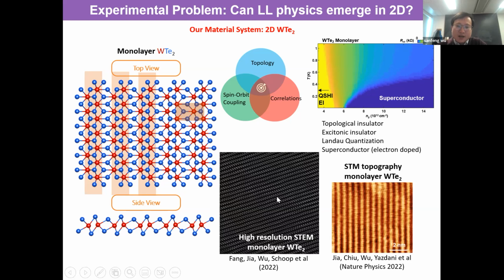The first image here is the transmission electron microscope. You really look at the atomic lattice, where the bright spot is a tungsten atom. You can clearly see a single layer of tungsten ditelluride has this Quasi-1D, 1-dimensional chains here. And the image on the right is the STM topography, which means there's an electronic state that you can also see 1-dimensional chains very clearly.